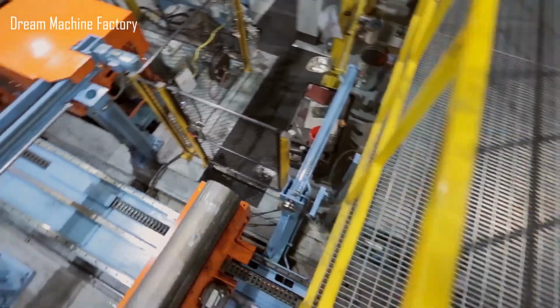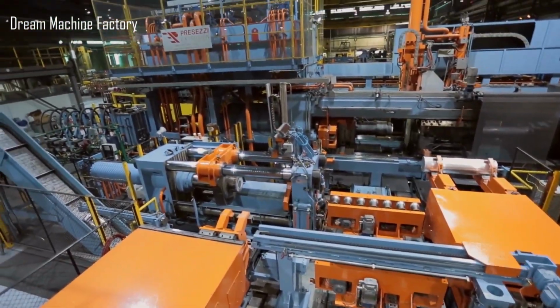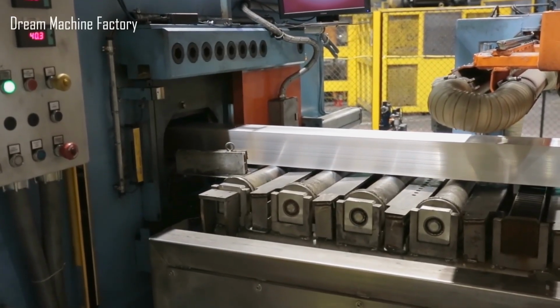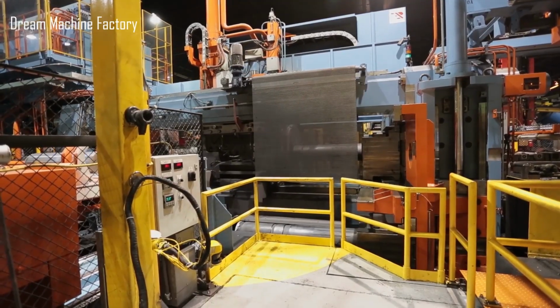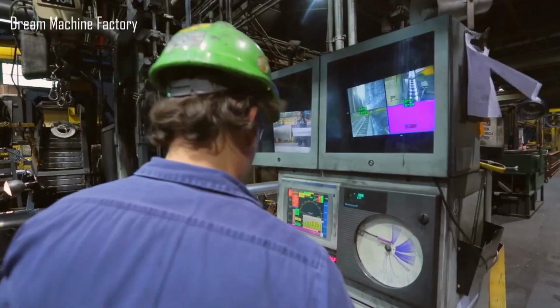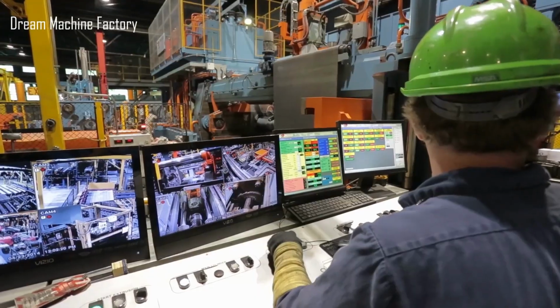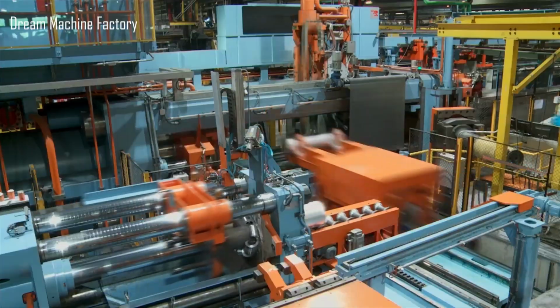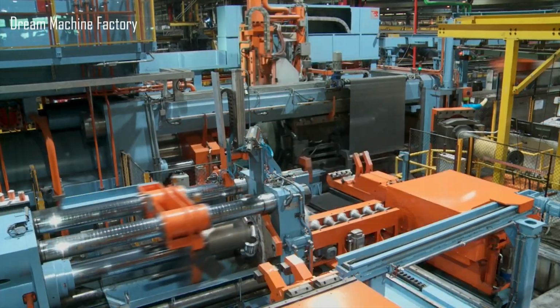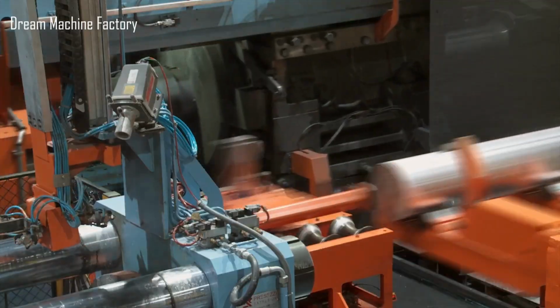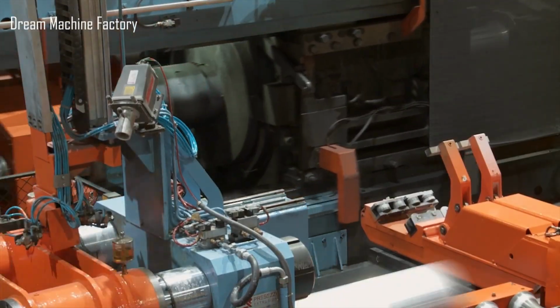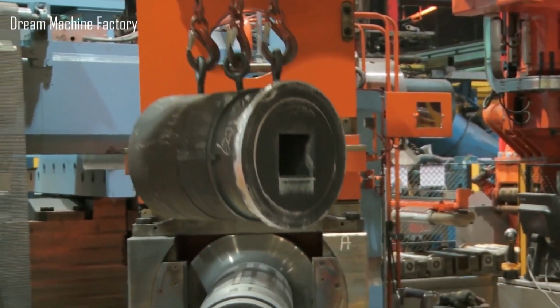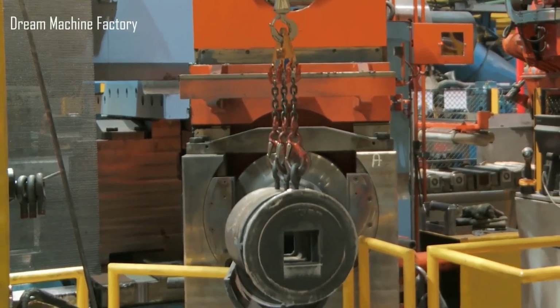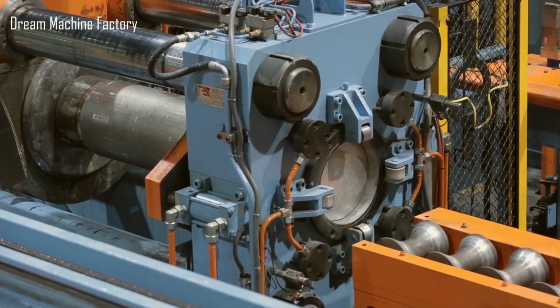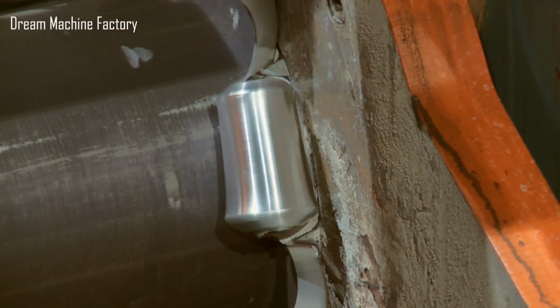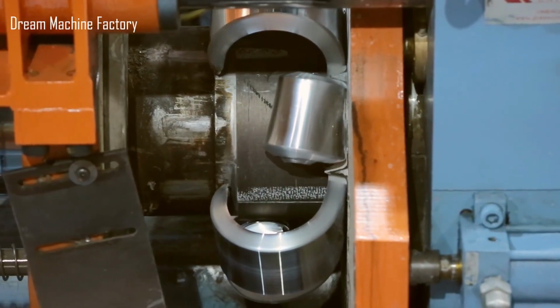Indirect extrusion, in contrast, reduces friction significantly. Here, the die is mounted inside a hollow ram, and instead of pushing the billet through the die, the entire container and billet move together toward the stationary die. This method results in lower friction, more uniform temperatures, and consistent dimensions and grain structures. However, indirect extrusion is limited by the size and complexity of shapes it can produce, because the tooling must fit inside the hollow ram. Additionally, billets must be scalped to remove the outer layer before extrusion, ensuring surface quality.